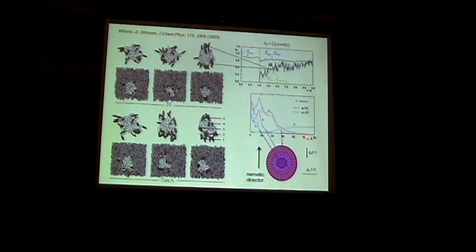And from the density distribution in different directions, we found that the most deformation is happening in the spacers and in the mesogenic units. And the central core is mostly keeping spherical shape.